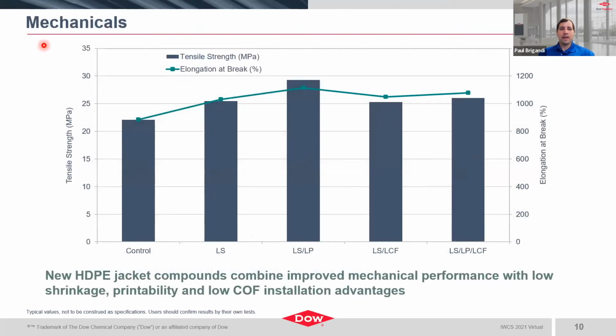Now we look at the mechanical properties. So in this case, really looking at the tensile strength and the elongation at break. Really what we're looking at here is maintaining the performance that the industry knows and wants for these materials, compared to the control. But actually what you see is a slight improvement in mechanical properties for the various materials. So whether it's low shrink or all the way up to the low shrink, laser print, low COF, we're able to take advantage of these added functionalities and again, maintain the mechanical performance of the material on the cables.